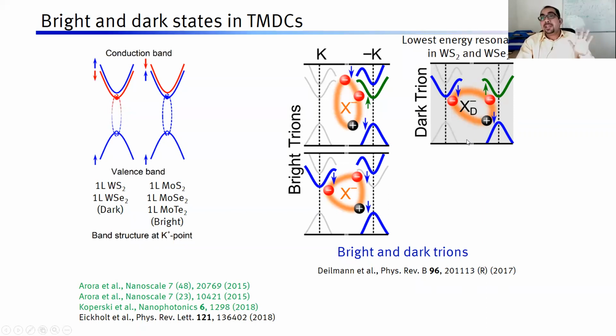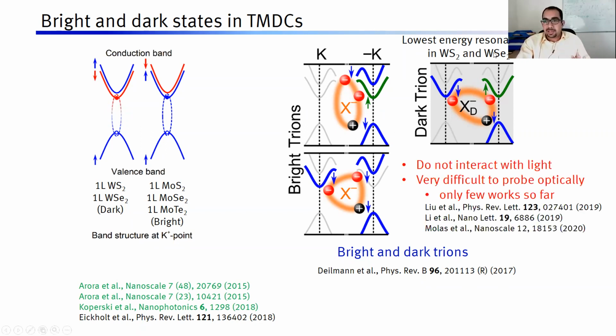Therefore, they would dominate the optical properties, because now they are the lowest energy. They would freeze every carrier possible at low temperatures, and they would start dominating. The problem is that they do not interact with light, so they are very difficult to probe optically. There have been only very few works so far. But how do we understand their effect on the optical properties? Let's see.